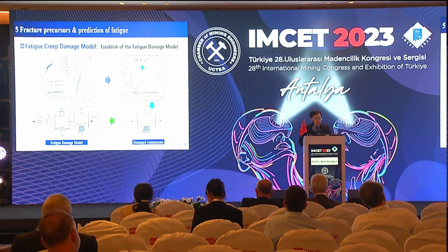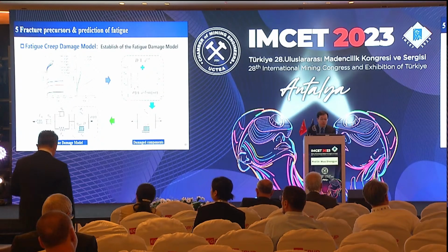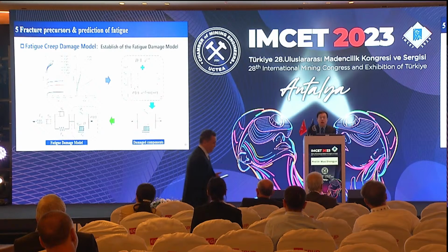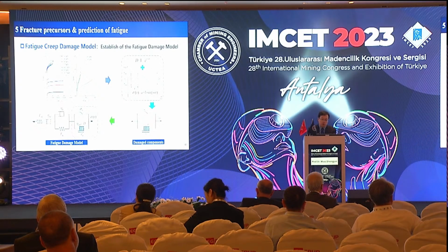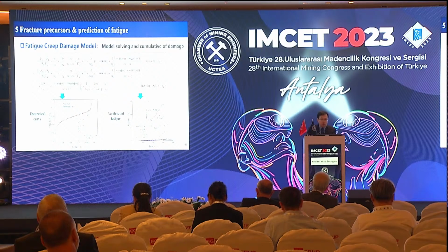Based on the previous studies on fatigue ultimate deformation and fatigue precursors, we introduced a viscoplastic damage element with stress threshold, strain limit, and damage variable. Then we connected this element in series with the Burgers model, resulting in a fatigue damage rheological model. Next, we ran the model under sine wave loading. The theoretical curve obtained from the model aligns well with the test result and accurately reflects the stepwise damage evolution characteristic of rock under cyclic loading.